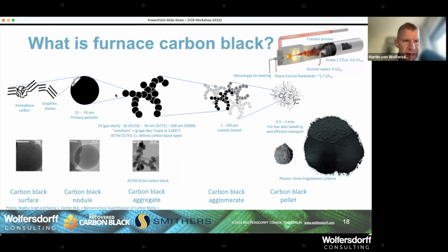But back to the primary particles in the ASTM range, they are typically between 10 and 95 nanometers. So this is a nanomaterial, but they're never alone. They are clustered and really fused together at a high temperature into aggregates. And the aggregates, they are very different for every type of carbon black.